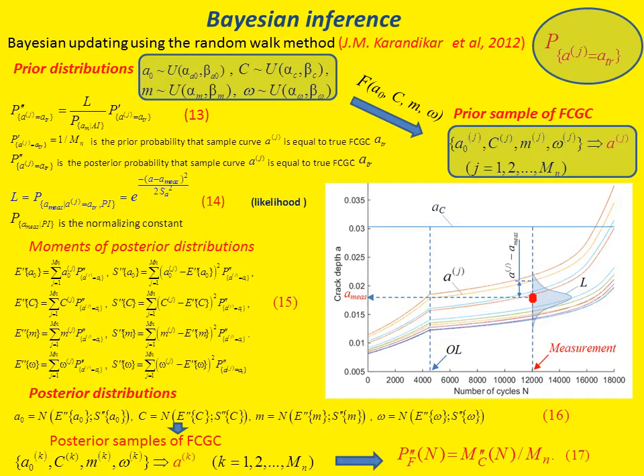For each sample curve, the Bayesian rule can be written as equation 13. Here, P' is the prior probability that a sample fatigue curve a(j) is the true fatigue crack growth curve. All sample curves are assumed to be equally likely. It means that for all sample curves, P' is equal to 1 divided by Mn. L here is the so-called likelihood function that describes how likely it is that the sample curve is the correct curve, given the measurement result at a particular number of loading cycles n. If the sample curve lies near the measurement result, then its likelihood value is high, otherwise it is low.